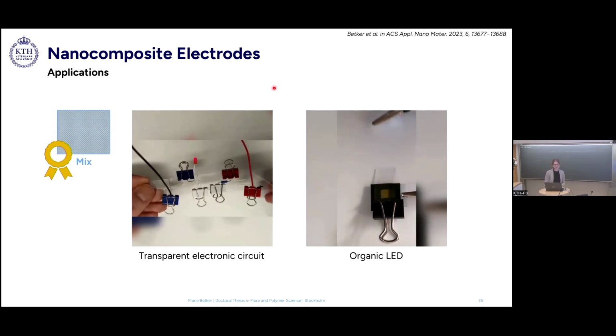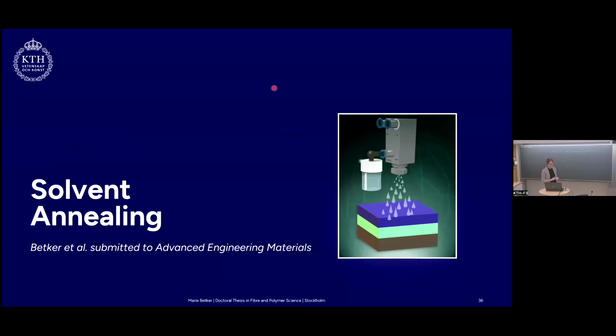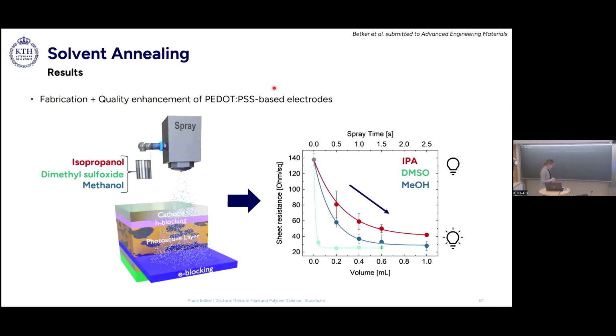Okay, so now you saw many applications or things you can fabricate with spray coating. In the final section now, I want to show you that you can use it for a different approach. So in this project, we used spray coating to first fabricate PEDOT-PSS-based electrodes. And then in the second step, we used the same spray setup to enhance the quality of these electrodes, to make them more conductive. And we did this by using 3 different organic solvents: isopropanol, DMSO, and methanol.